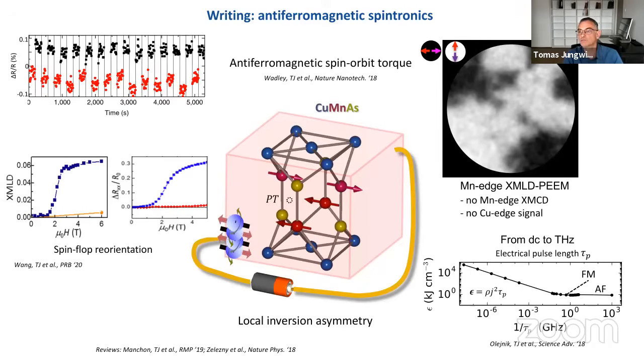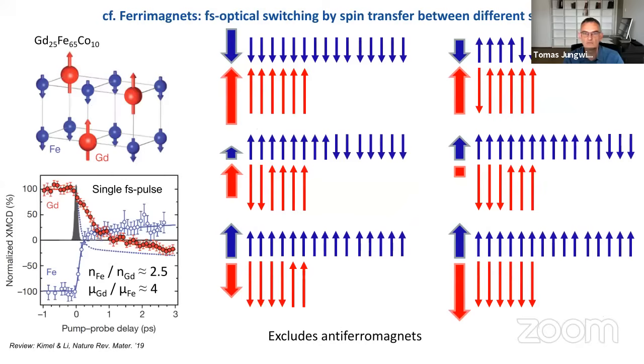Of course, then the question is, what is the ultimate speed, or what is the minimum pulse length that you can use to switch such an antiferromagnetic device? But if we go beyond the terahertz, if we go beyond 1 picosecond, we actually are not anymore in the regime of generating spin orbit torques by electrical currents, but we enter the field of optical switching. And traditionally, in ferromagnets or ferrimagnets, systems with a net magnetic moment, ultra-fast switching by single femtosecond pulse has been a field completely separated from the electrical switching by spin torque mechanisms.